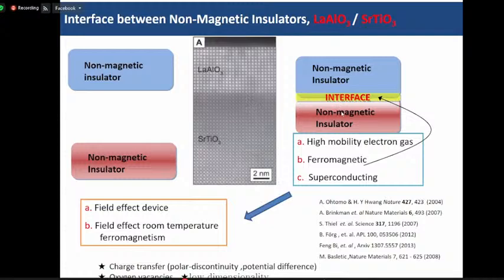So researchers wonder why it happened. There are many reasons: charge transfer due to the polar discontinuity, potential differences, oxygen vacancies, and low dimensionality because of the films, and then reorientation of spins and orbitals at the interface. Or sometimes the structures change at the interface. There are many reasons.